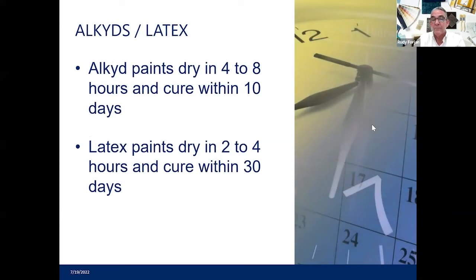So alkyd paints, the oil-based paints that we talked about, will dry in about 4 to 8 hours, depending on the kind of resin that you're using. And they're going to cure within 10 days, pretty quickly, because that's just the process of how the alkyd resins work. Latex paints will dry in 2 to 4 hours, generally a lot less than 2 to 4 hours. But look how long it takes for it to cure. So this is the type of thing that you have to take into account when you're painting, specifying paints, or planning to use paints.